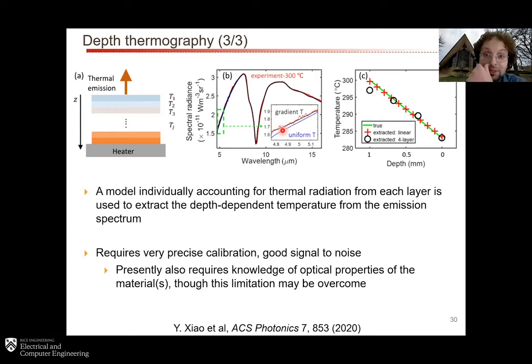So this theoretical calculation in blue that's labeled uniform temperature is essentially assuming that every one of these layers is at the same temperature. So this is kind of your typical assumption of thermal emission measurements. Whereas this black line over here is a spectrum that's calculated from this kind of model where we assume different temperatures. And so from this tiny difference that's hidden within this little region of the spectrum in which you have to zoom in to be able to see it, from that we can do a temperature extraction where we say, okay, so at the very top surface, the temperature is indeed almost 300.